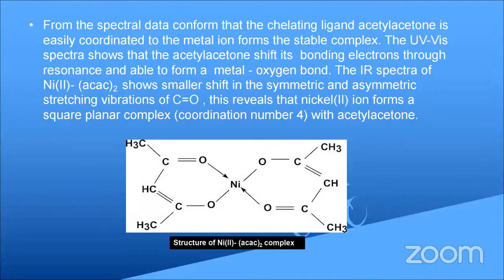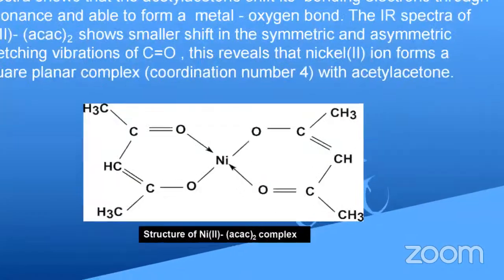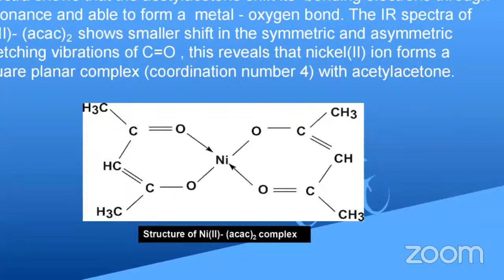From the spectral data, we show that the bis-acetylacetone nickel(II) complex shows a smaller shift in the symmetric and asymmetric stretching vibration of carbonyl. This reveals that nickel 2+ forms a square planar complex with acetylacetone, with coordination number 4. The structure of the bis-acetylacetone complex will be this.